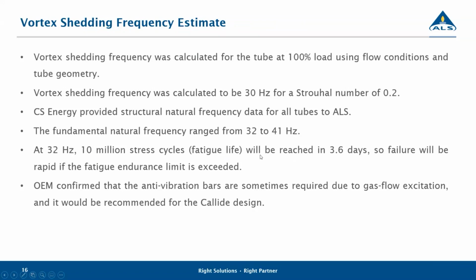There was a condition that occurred where these oscillations that the tube sees was sufficient to cause damage over quite a short period of time. The OEM also confirmed that anti-vibration bars are sometimes required due to gas flow excitation and would be recommended for the Callide design.